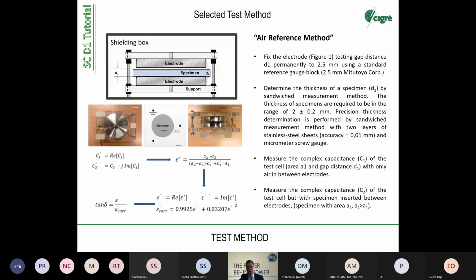And finally, you need to measure the complex capacitance C2 of the test cell, but with the specimen inserted. And from these values, you can get the tangent delta and the epsilon R value. So the epsilon 1 value is the real part of the permittivity. Then you have to calculate the epsilon 2, which is the imaginary part. And from both parts, you have a correction here on the real part. You have to do this because of the air reference. And here you calculate the tangent delta, the loss factor, as epsilon 2 divided by epsilon 1 corrected.